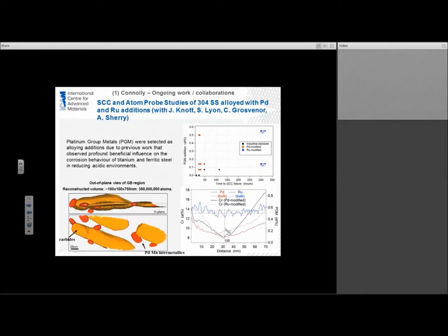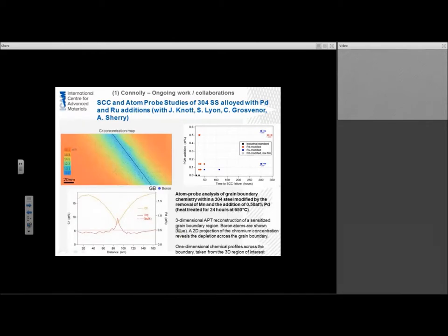What we did is we made another alloy without the manganese. The next slide shows you the results of the stress corrosion cracking. If you look at the top right, this is the symbol that represents the testing that we did on the palladium modified low manganese alloy of the 304 stainless. We see similar performance to that we saw in ruthenium. If you look at the atom probe data, we see that we have an enrichment of palladium at the grain boundary whereas we still have this chromium depletion. We have the ability with this alloy system to have a sensitized microstructure or a chromium depleted zone that is not susceptible to stress corrosion cracking. This would be very advantageous for critical components where you have a threat of a cracking event.